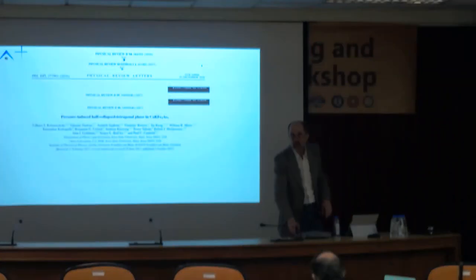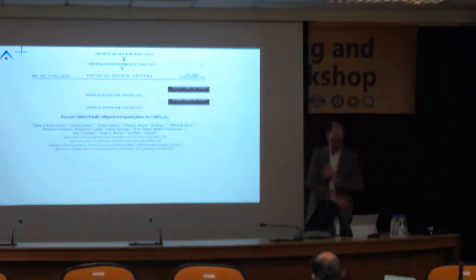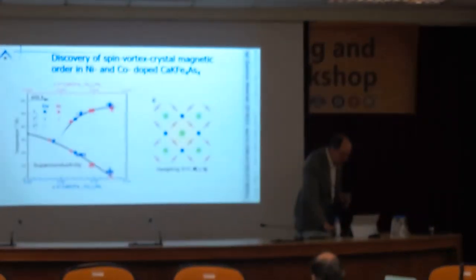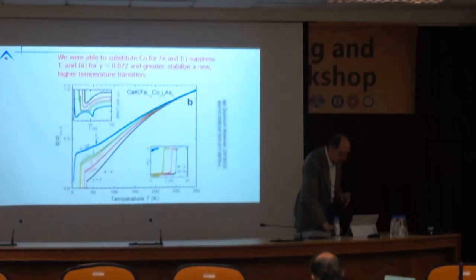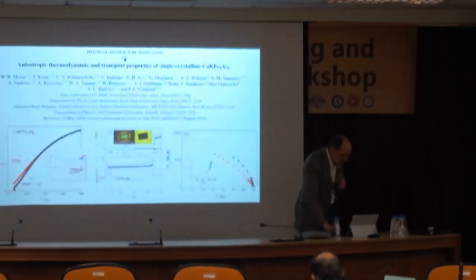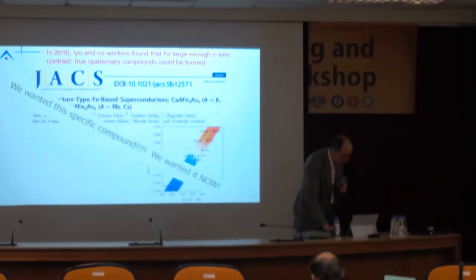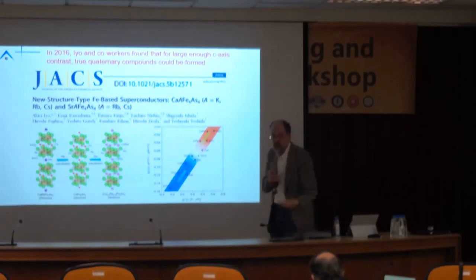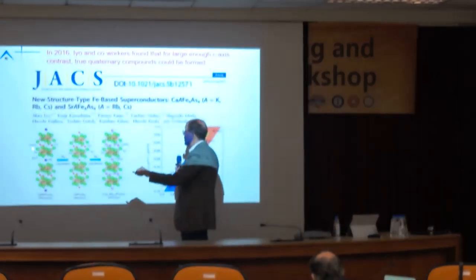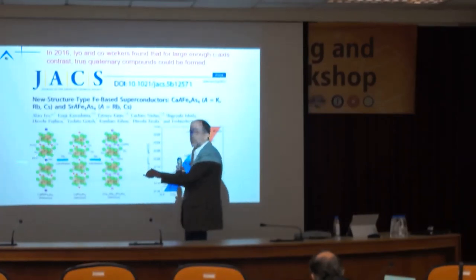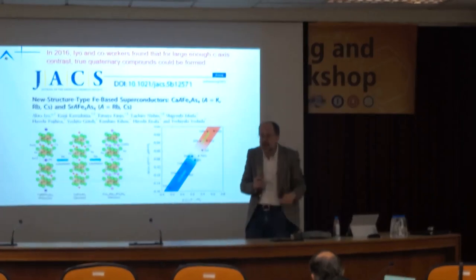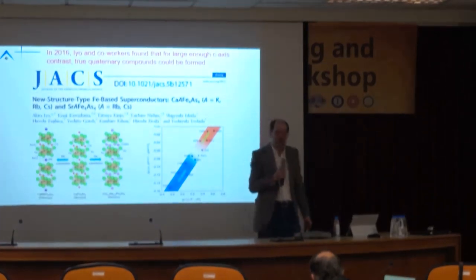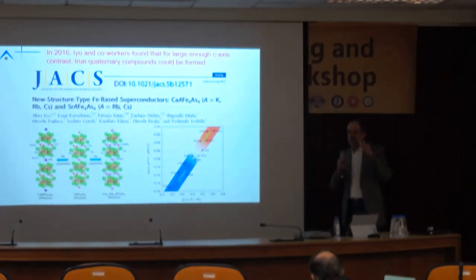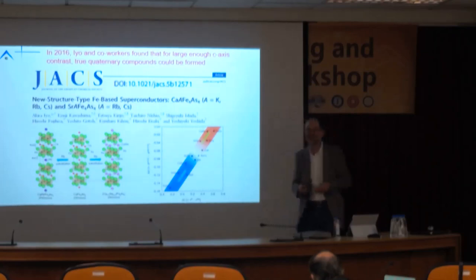On the 1144, since you've got inequivalent iron arsenide layers in there, when you substitute the cobalt and nickel and get the magnetic order, is the magnetic order the same in the equivalent magnetic layers? Is there any difference in structure along the axis? I think you're wrong in one sense. The iron layers are equivalent, because any iron layer has arsenic and calcium on one side, and arsenic and rubidium or potassium on the other. They're asymmetric, but they're equivalent. Okay, I was thinking double layers. We've had to wrap our heads around this quite a bit.